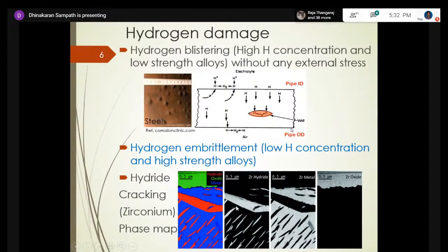The phase map will show, for example, that this material has got zirconium hydride, zirconium oxide, and pure zirconium. So the blue are all zirconium, and the red color is all zirconium hydride. The red color regions are very brittle compared to the blue, and the green one is the oxide, which is at the outer surface.